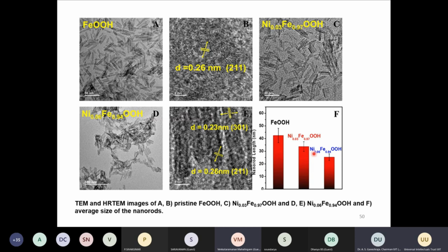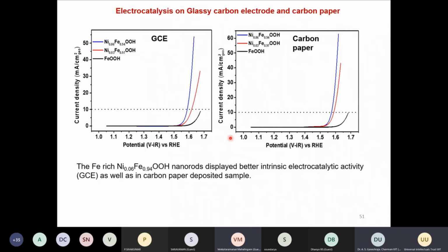but when we have nickel, what we observed is that the length of the rod decreases. So basically the rod morphology is retained, but we can change the rod length with the nickel amount using the same synthetic procedure. And here I have shown the electrocatalytic activity on the glassy carbon electrode and the carbon paper. The carbon paper is different because it improves the conductivity, whereas the glassy carbon electrode gives the intrinsic activity of the sample.